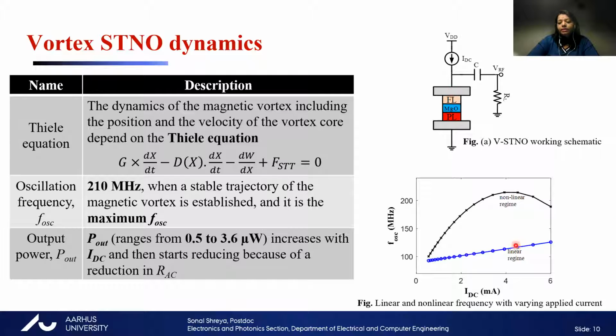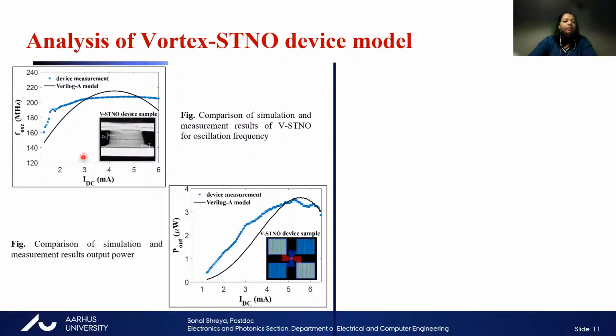And this is the measured and simulated results in the non-linear regime. We can see how the frequency increases with the increasing current. If we keep on increasing, then after a certain point, because the core reaches the circumference, it vanishes, so the frequency starts reducing. Here I present the comparison of the measurement and the simulation results. The model is in very close approximation with the measured results.